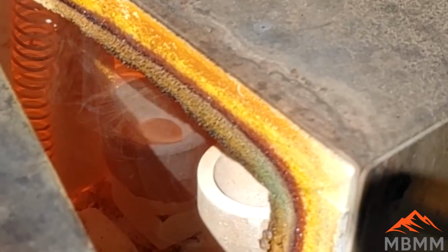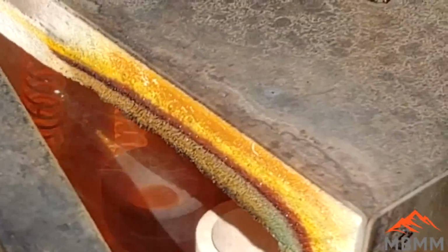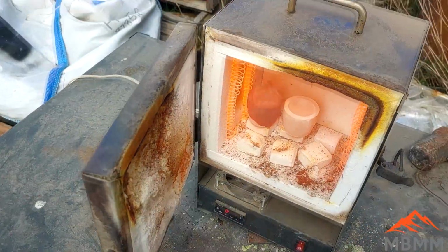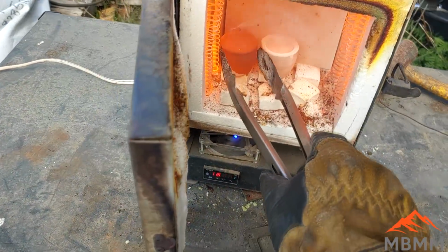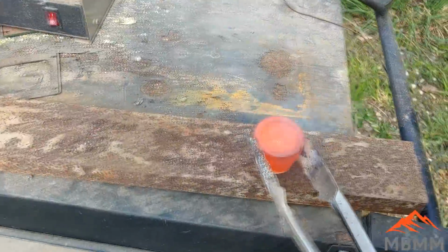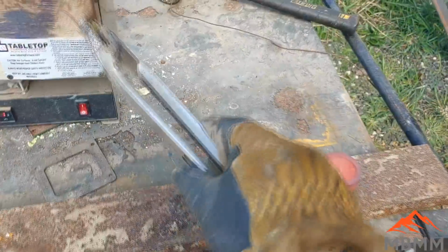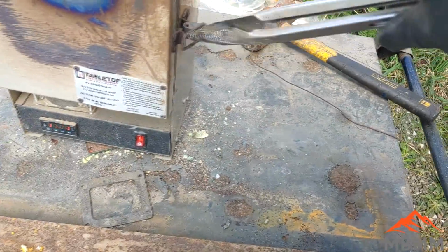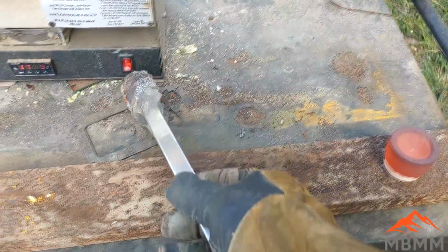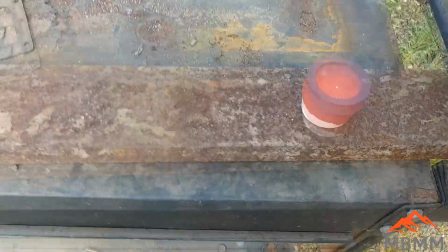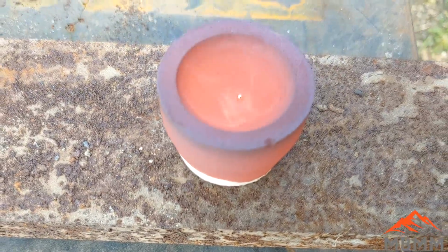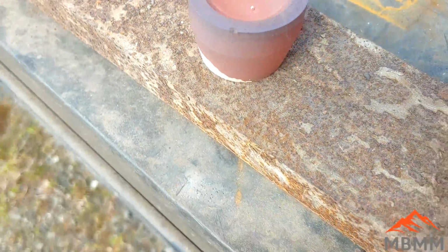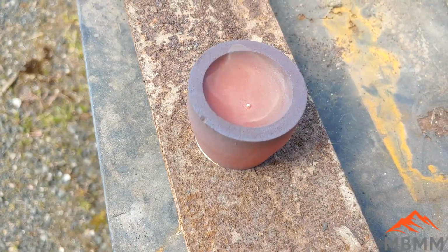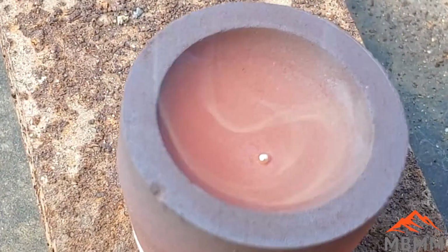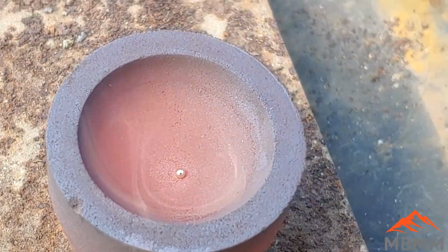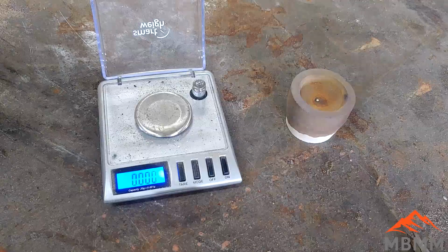It's a little magnesia cupel, and that's going to continue, and even a little bit of copper or a little bit of arsenic or a little bit of bismuth is going to also roll off there with the oxides. And as that goes all the way to completion, this little bead is going to be left with just the precious metals, the gold and the silver that won't oxidize in the atmosphere even at 1850 degrees. And then we can cool that down, pick the bead out, get it weighed, and then we'll figure out how much precious metals we have in our 100 grams worth of sulfides we started with.